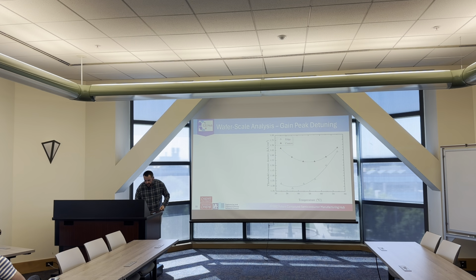What's physically at work there is an offset between the gain peak wavelength and the cavity mode wavelength, and that varies as a function of position on the wafer. So at the center, at room temperature, we have the case where the cavity mode wavelength is longer than the gain peak. That's as it's designed, so that when you operate at higher temperatures and higher biases, those two wavelengths will align. But at the edge, that's happening at room temperature at the biases that we're working with.